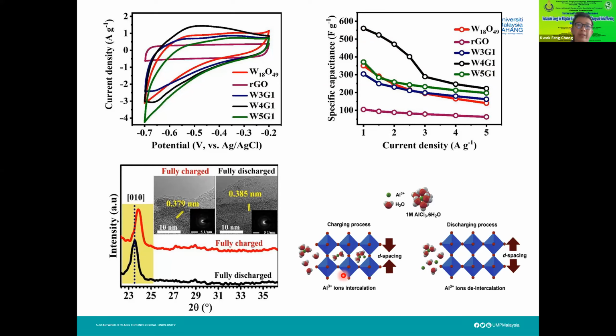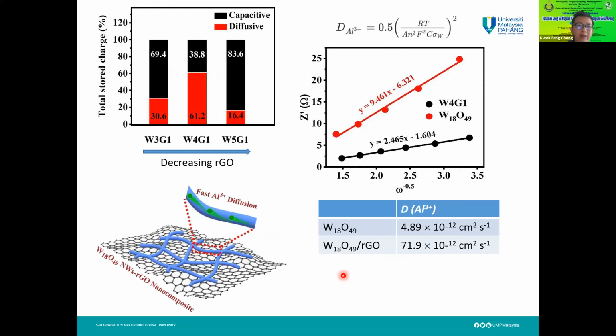But right now we want to prove our hypothesis, because at the beginning we said that we want to use the graphene to increase the diffusion of this aluminum ion. So we ran the test to study the diffusion coefficient of this aluminum ion within the structure. And we are able to come up with the calculation whereby, without the graphene, the aluminum ion diffusion in the tungsten oxide is roughly about 4.89 times 10 to the power -12 cm squared per second.